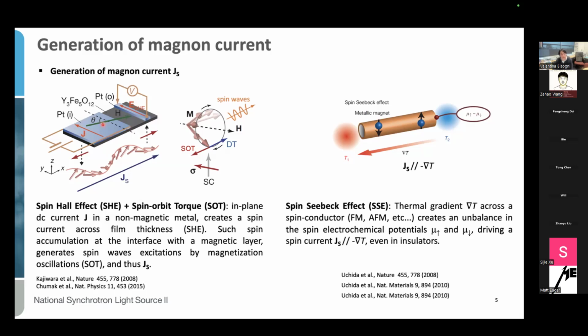Basically we have our conductor that is now a magnetic material, as represented here by this gray slab. On top, we have an electrode that should be non-magnetic, for example platinum. First, we realize the spin Hall effect in our platinum electrode by having an electric current going through it. This electric current generates a spin current across the thickness of the platinum electrode. Because of the spin current by spin Hall effect, we now have a spin accumulation at the interface with the underlying magnetic material. The spin accumulation can generate an oscillation in the magnetization of our magnetic conductor by spin orbit torque. Because of this, magnons get excited in the material and they can finally generate a magnon current.